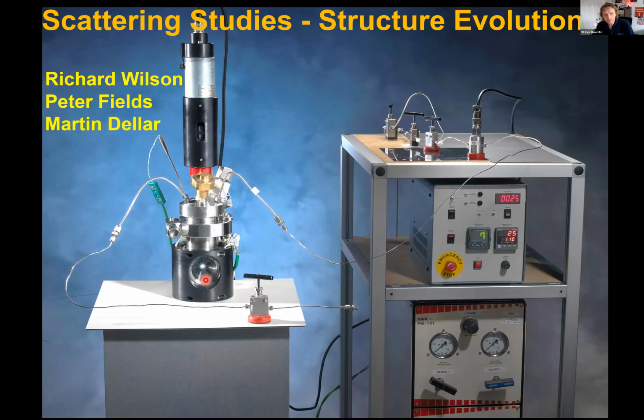These windows have to allow X-rays to pass through, so they have to be very thin, but also they have to hold back a pressure of maybe 200 to 400 times atmospheric. So how do we do that? How do we get thin windows and hold back a high pressure? The original vessel I showed you at the beginning of my talk had a sapphire window, but this is about 5 centimeters thick, and that just wouldn't pass X-rays.